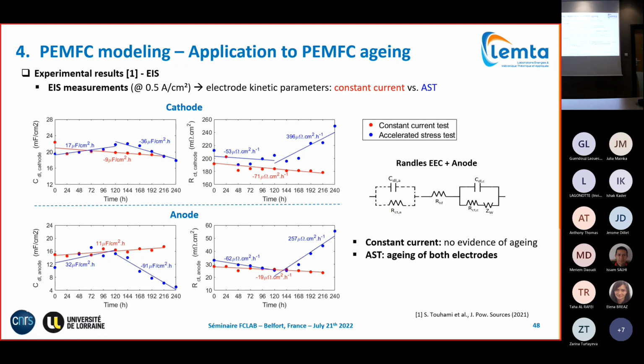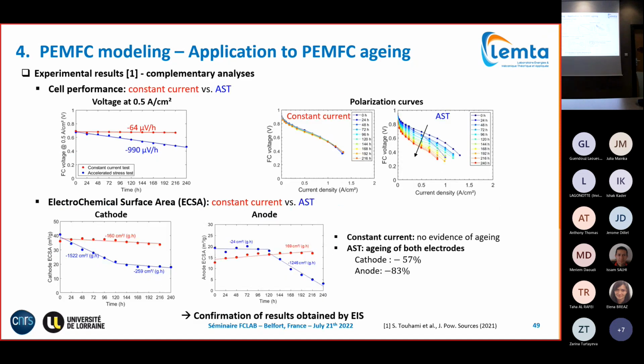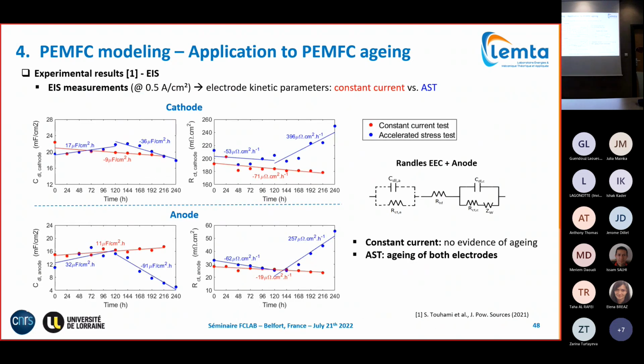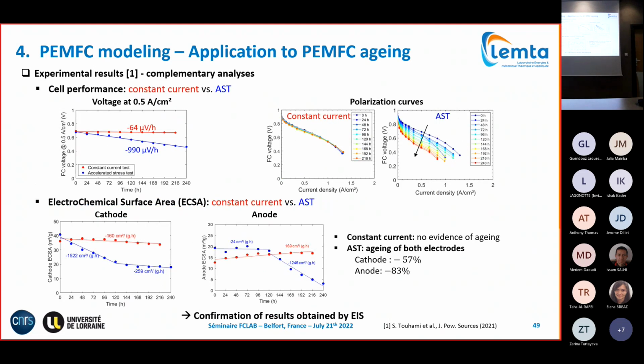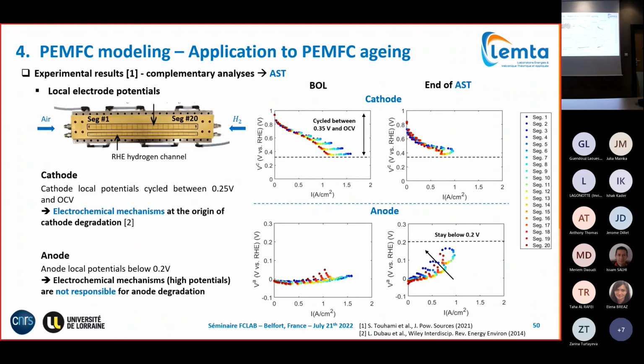Here, electrochemical impedance spectroscopy for the moment just serves us to say, okay, it degrades. Then we have our other techniques that give us more insight into what really happens. This one informs us as well of a decrease of performance. EIS tells us a decrease of performance, which should lead to a degradation of the electrodes. This one here confirms, yes, electrode degradation, a reduction of the active area. And what tells us more about the physical origin, whether it is electrochemical, so corrosion processes or others, are the local potentials.